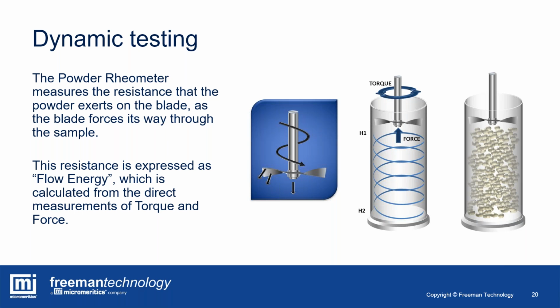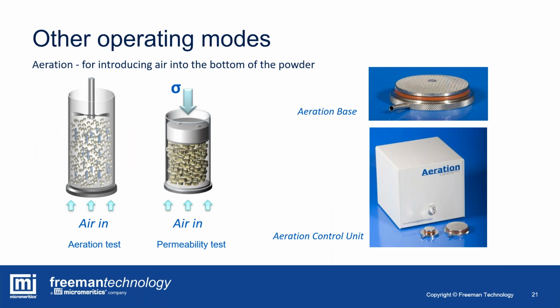We can actually do that whilst also introducing air. So with the addition of an aeration control unit, which you can see here in this right-hand image, and an aeration base, which goes into the bottom of the powder vessel, we can introduce air from 0 to maximum requirement in order to aerate or even fluidize the sample. And the purpose of that is to assess how the flowability changes as a function of aeration. I'll talk in some more detail later about that.